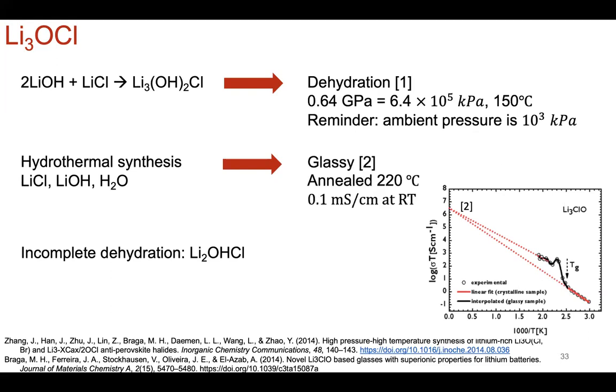extreme for processing. The next type of synthesis for producing these types of compounds has also met with a little bit of controversy. All right, I won't understate that. Has been met with a lot of controversy. In terms of hydrothermal synthesis, right, you load these precursors in H2O, so that makes it hydrothermal under high pressure, and then anneal, anneal at 220C. You get what's called this glassy, but really it's sort of, I would say, just sort of disordered. There's some glassy crystalline component. It's actually semi-crystalline, but the notation in the literature is that classified as glassy. So I'll go with that for now before I put my spin on it.